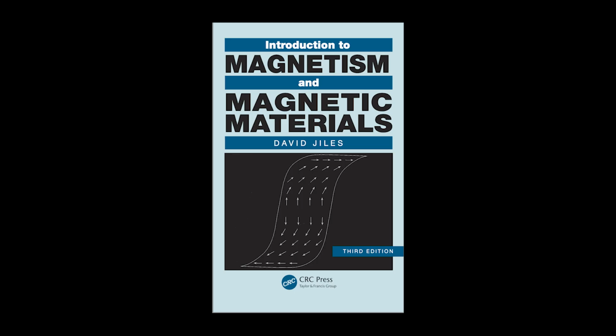First, you have the localized electron theory, or the Heisenberg model. This assumes the magnetic electrons are fixed and deeply bound to their atomic site. And this works perfectly for the lanthanides like gadolinium, whose 4f electrons are very isolated. Okay, and then there's the other theory. The itinerant electron theory, or band theory. This assumes the magnetic electrons are in the outer, shared shells, and they behave more like conduction electrons, just moving freely throughout the solid. And this is necessary to describe the critical 3d transition metals, iron, nickel, and cobalt. The ones that matter most for technology. The ones that matter most.